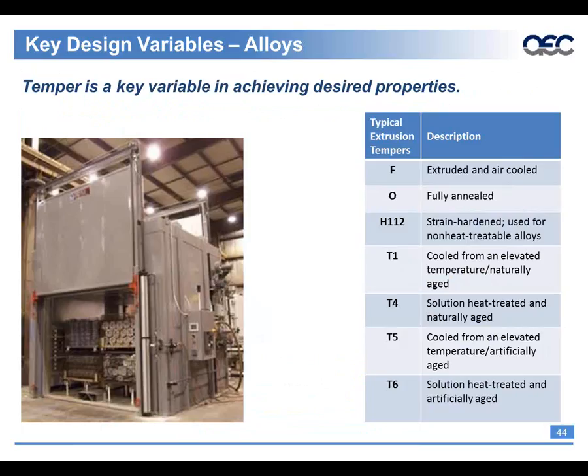T1 temper is very good for bending applications. So if you have radius windows, especially very large radius windows in commercial buildings, libraries, things like that, T1 temper is a good place to start. Though the material will naturally age over time, so you want to make sure you have fairly new material out of the manufacturing facility within a couple of weeks. Otherwise, through the natural aging process, you won't be able to bend it as well.